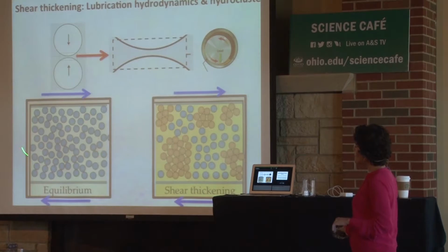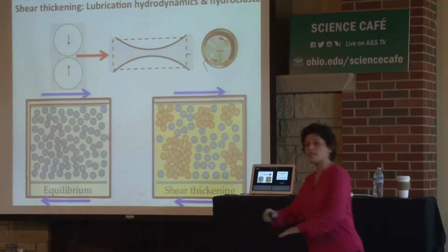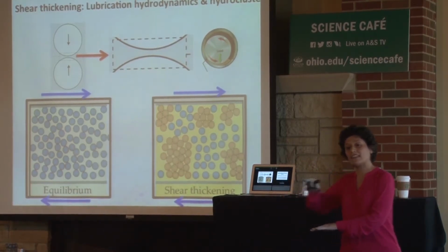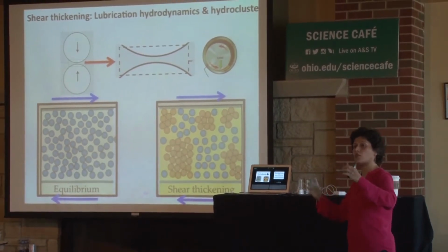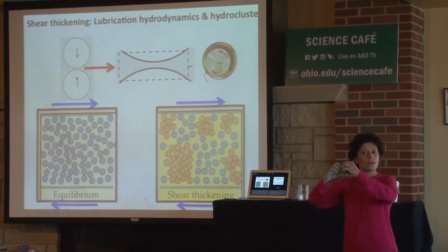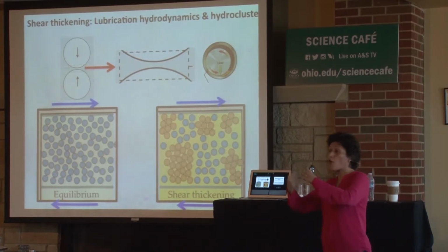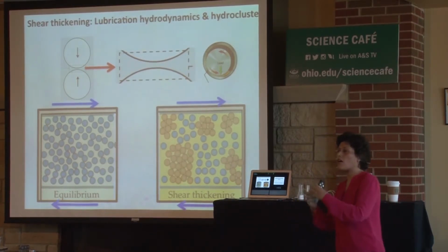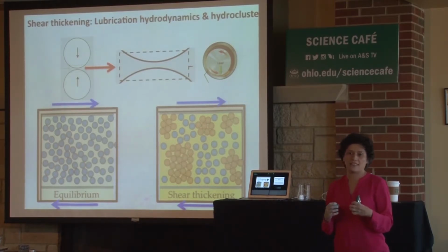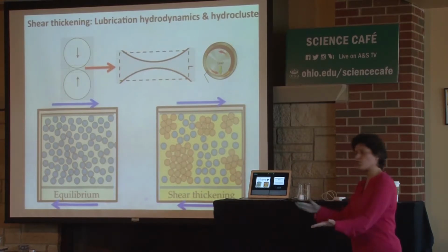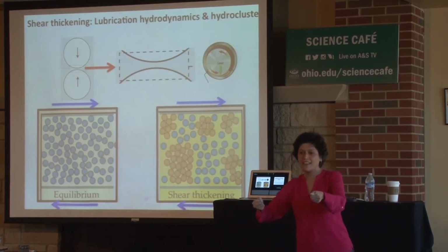They say that suppose you have your cornstarch in water, okay, and you start shearing it. When you start shearing it, as you shear it faster and faster, like you're stirring it faster and faster, what happens? Grains of cornstarch come close to each other, okay? When they come close to each other, a film of water forms between them, right? They make that lubrication force so that they never touch, but they can never escape from that. And the reason is that if you have two smooth surfaces, like glass, and you want to attach them, it's very difficult to do so.